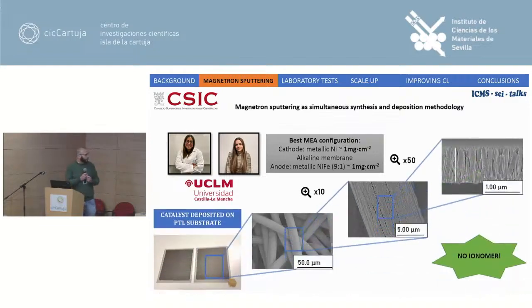Here you can see how these kinds of catalytic coatings are deposited over a porous transport layer, a commercial porous transport layer, and here you can see how this catalytic coating is distributed among this fiber, depicting a mesoporous structure that is formed by these nanocolumns that grow from the bottom of the substrate to the top. One particular characteristic of this kind of catalytic coatings is that it doesn't have any kind of ionomer, which is a molecule that usually is used in this kind of catalytic formulation when they are prepared by wet routes that helps to fix the catalyst to the substrate.